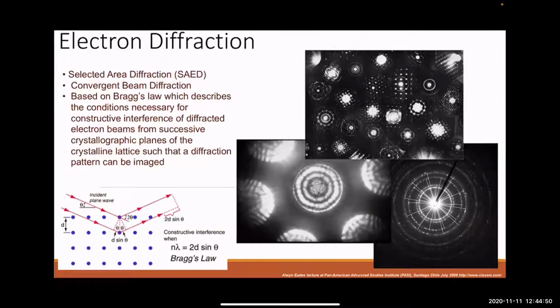Analyzing these diffraction patterns can be a bit complex, as you might imagine, but it's very simple to get a diffraction pattern. You can get one in minutes, and very quickly, in a matter of seconds, tell if it's polycrystalline, or a single crystal, or amorphous, just by looking at the diffraction patterns. So that's something that's very useful for a lot of people as well.